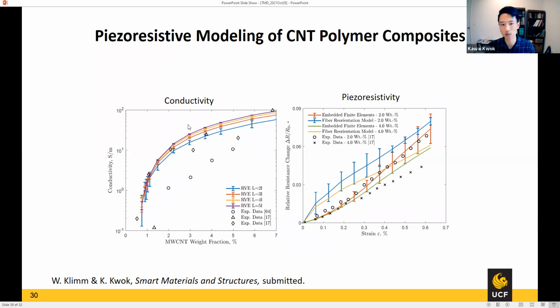But that is the zero-strain conductivity plot, and on the right-hand side is the resistance change versus strain response, so this is the piezoresistive model. Again, we have two ways of capturing the deformation of the network. One is called embedded elements, where the carbon nanotube floats around in the RVE and follows the matrix deformation. The other is called a fiber reorientation model. That model was proposed in the literature some years ago and has been the mainstream model that everybody is using. It is based on an affine deformation of the network. So there are different assumptions behind these two kinematics models, and we try to compare them.